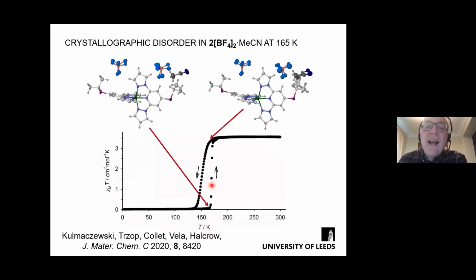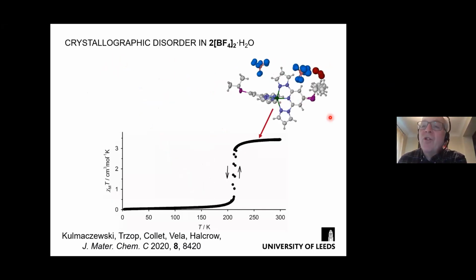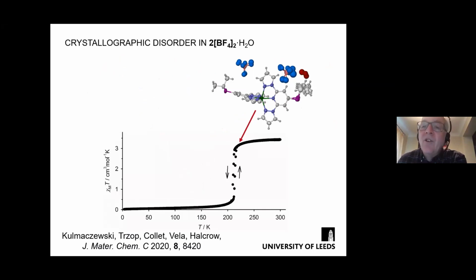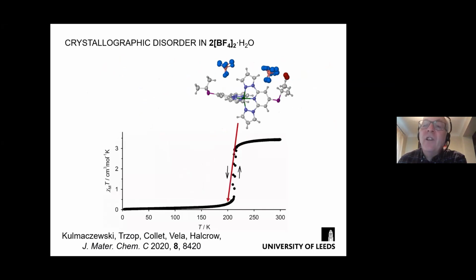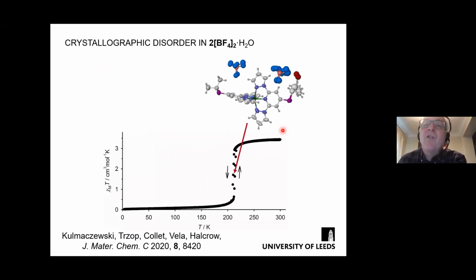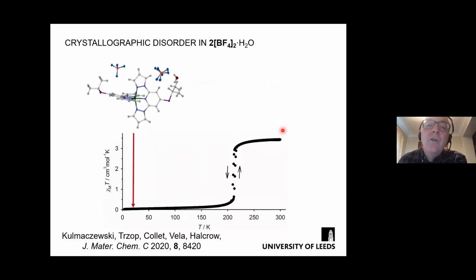Now, to understand the different shapes of the spin transitions, you think that this disorder might be important. So if you compare, for example, the acetonitrile solvent in the high spin and the low spin form at the same temperature inside the hysteresis loop, okay, we're losing a little bit of disorder in the solvent, but the disorder in the anions, for example, does not change. And if you look more generally, this is the water solvate now. If we cool it down, looking at the disorder, now we're doing the spin transition. We've lost a little bit of disorder now in the isopropyl group, but the rest of the disorder is still there. And we only lose the rest of the disorder at lower temperatures. So I think the disorder is not directly connected to the spin transition.